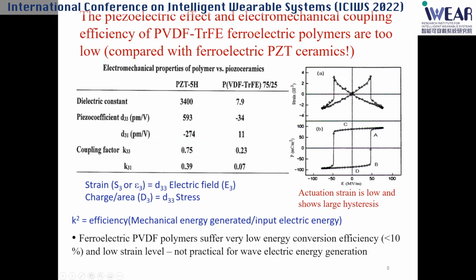One of the fundamental reasons is the material's piezoelectricity. Although PVDF-TrFE is really the best ferroelectric and piezoelectric polymer material in the market, its piezoelectric electromechanical coupling is still much below, for example, piezo ceramics. The piezo coefficient of ceramic is about 20 times higher than polymer—this means with the same applied electric field, the strain generated in the polymer is 20 times smaller than ceramic. Also, the electromechanical coupling in ceramic, for example with k33, is about 3 to 4 times higher than polymer, and energy conversion efficiency is proportional to the square of this coupling. This means the polymer's efficiency is about 10 times smaller than ceramic. That's why, even after many years of research, no practical device has reached commercially viable performance.